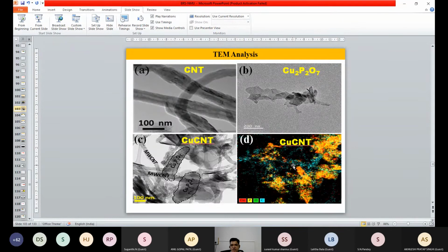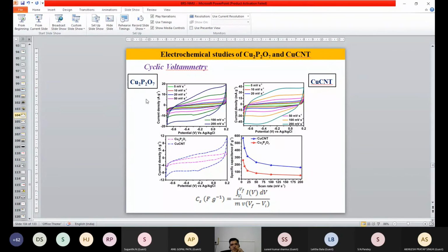And this copper phosphate, with its fibrous-like network and microflowers, gives very high surface area. Also, we have calculated the electrochemical active area. We have also calculated surface area by using BET analysis, right? And we have correlated that, so that you can see how this fibrous morphology gives not only porous area but electrochemical active surface area on the carbon nanotube. So here inside this one, you can see this is Cu2P2O7 on stainless steel, and this is the combined composite, and this is for copper phosphate.